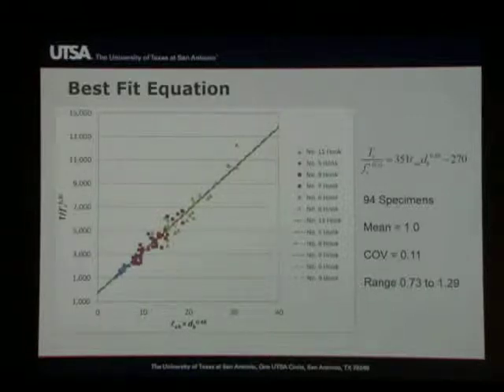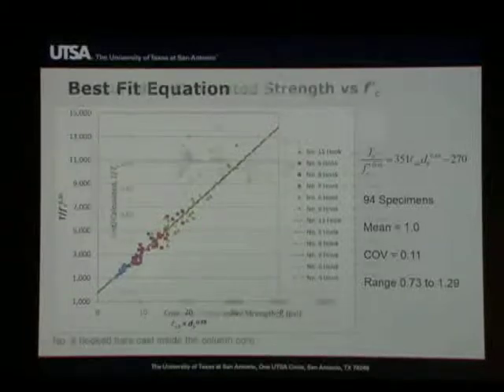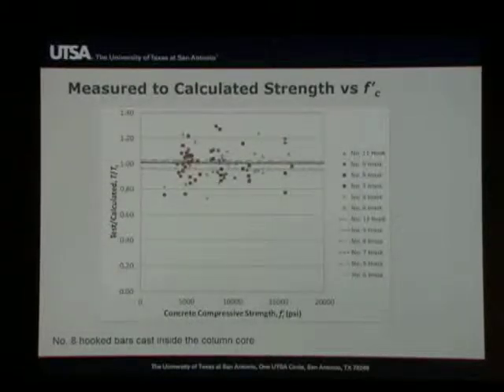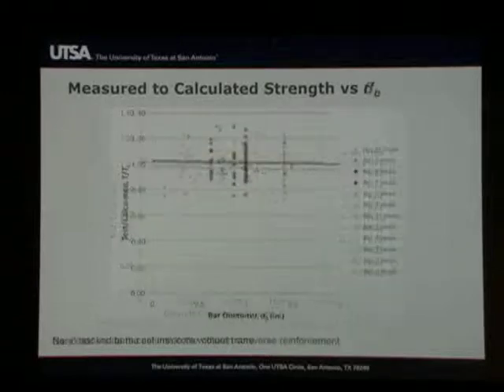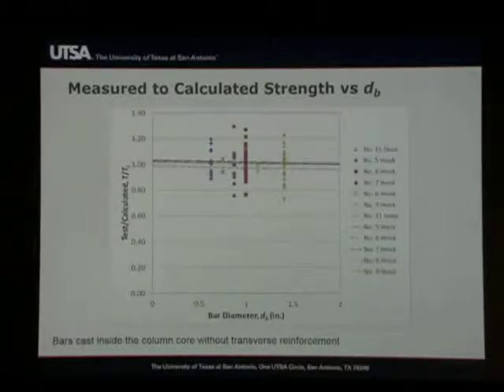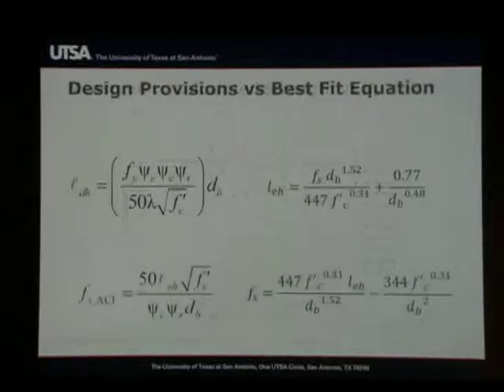And you obtain a best fit line, and you obtain a pretty decent coefficient of variation. Then you start to study the variations of other variables with respect to that. When you do this type of regression analysis, then you start to see the lines no longer have a slope. So here we see that we're objective with respect to compressive strength. We see that we're objective with respect to bar diameter. So all those differences have gone away.